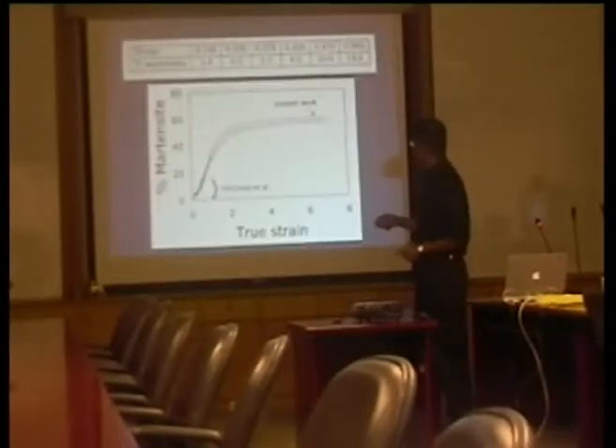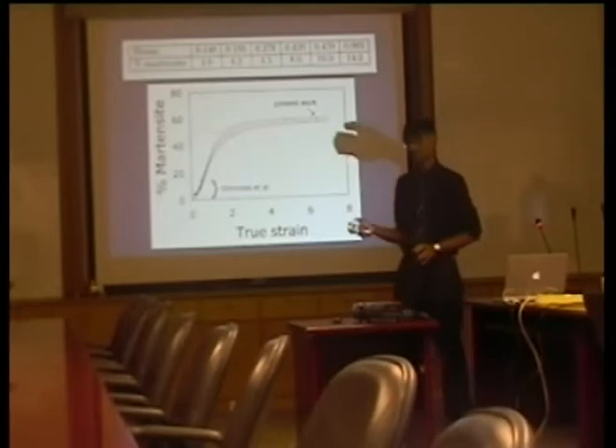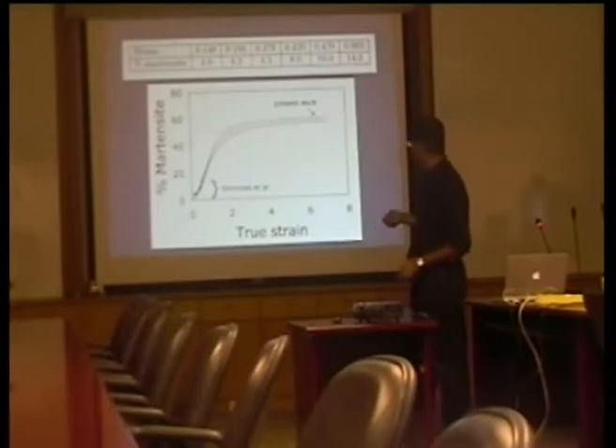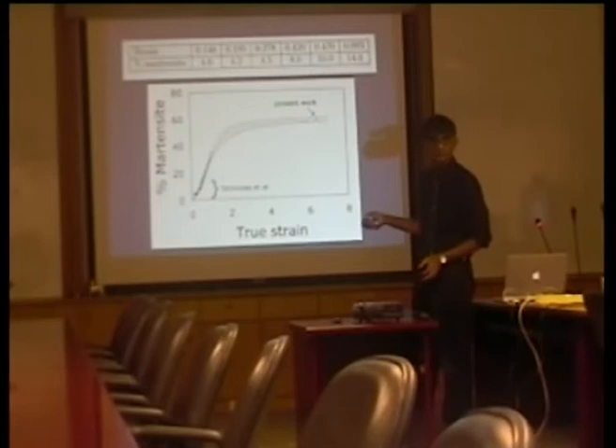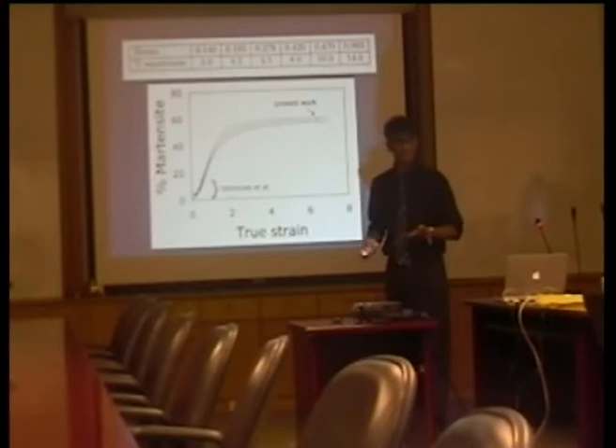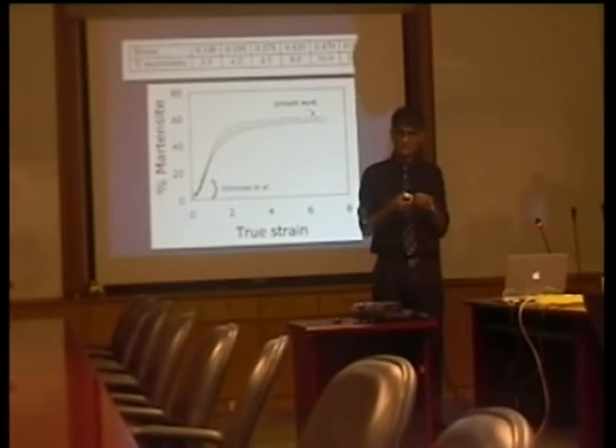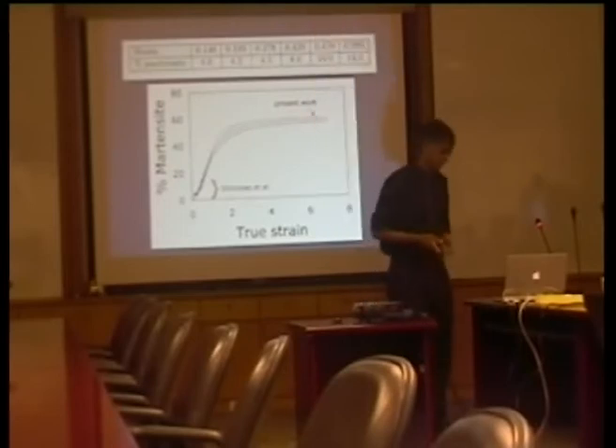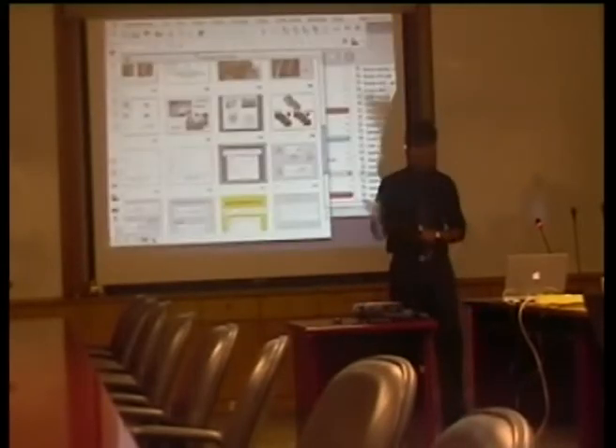Yeah, so look. This is a completely independent curve derived by fitting small strain data and very large strain data using the neural network model, and that also predicts that we should get stabilization at around a true strain of 2. Okay. So it's really important that somebody, I hope MIRDC, helps us to do an experiment where we can experimentally verify that yes, stabilization actually happens at a true strain of 2. The physical theory and the neural network both predict the same number.